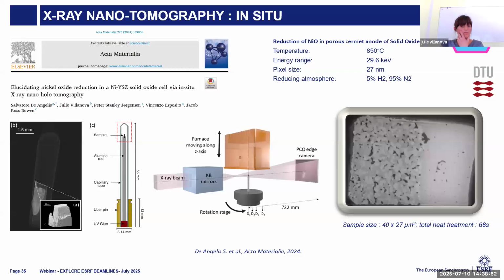The samples can also be mounted under a specific atmosphere. So here you have a piece of solid oxide cell that is mounted on top of the alumina rod in a capillary filled with hydrogen. And so then we introduced this sample mounting in the furnace, heating up at 850 degrees C. And then we were looking at what was happening in the sample.